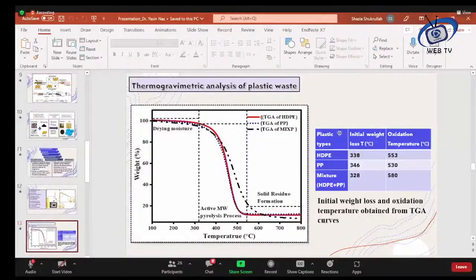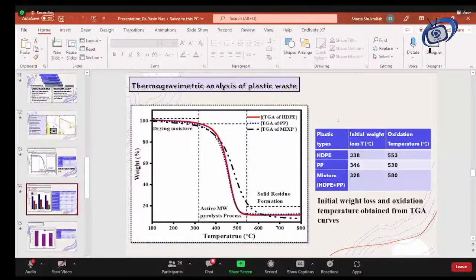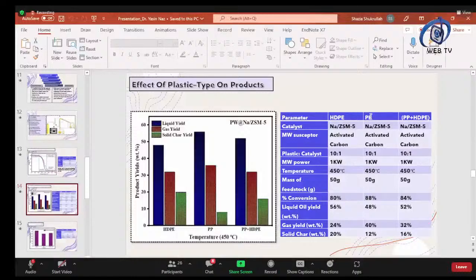So here we use three types of plastic: high density polyethylene, PP, and the mixture of PP and HDPE. We use sodium ZSM5 catalyst. We use activated carbon as a heat susceptor. Then we keep the plastic to catalyst ratio at 10:1. We use a microwave power of 1 kilowatt, and the temperature of the process was kept constant at 450 degrees Celsius, and the mass of the feedstock was fixed at 50 grams.